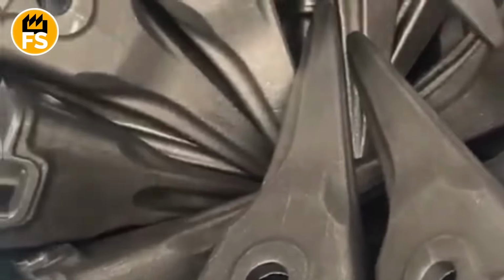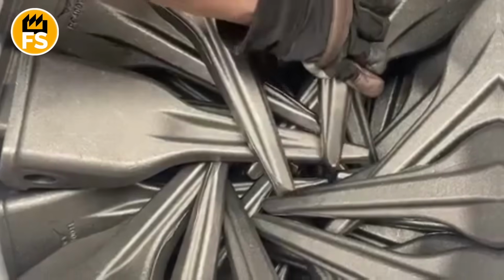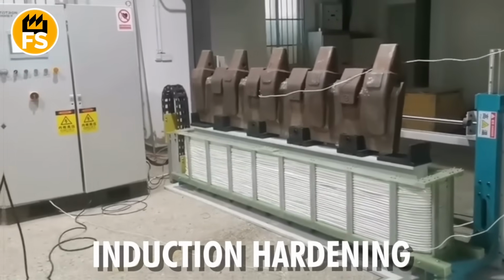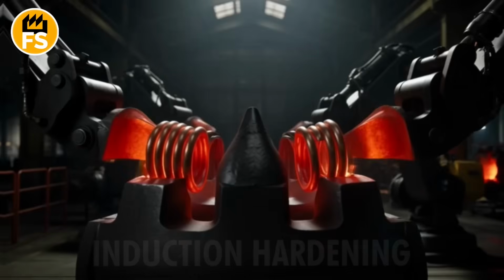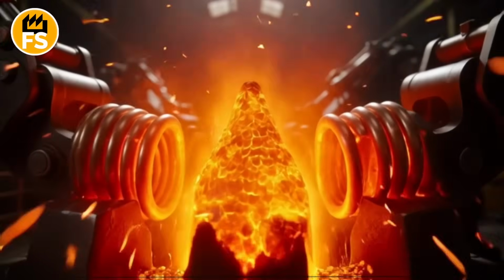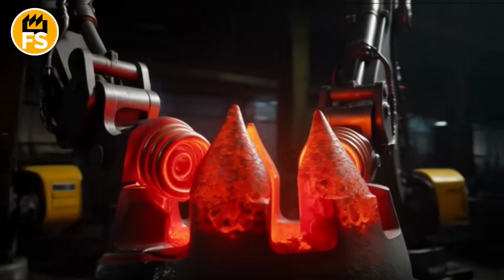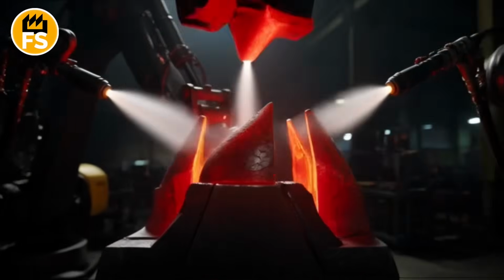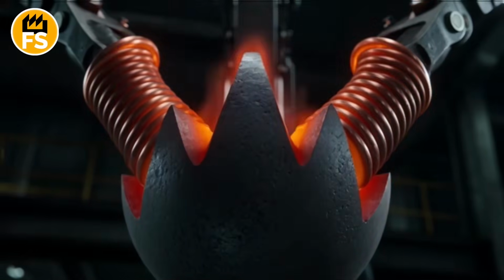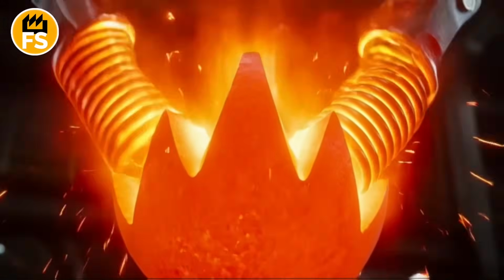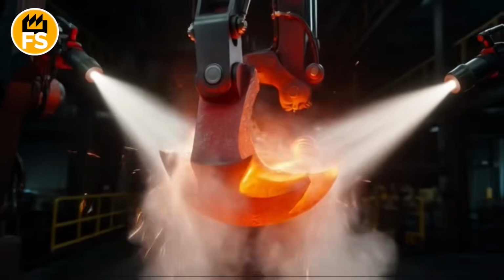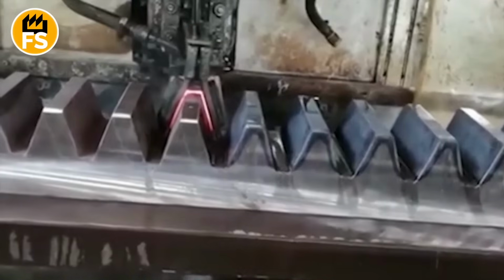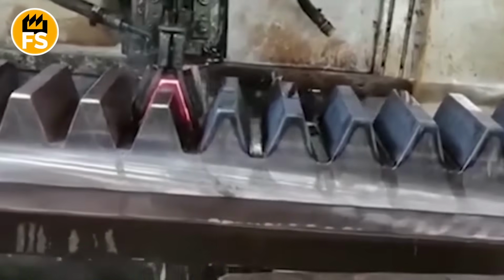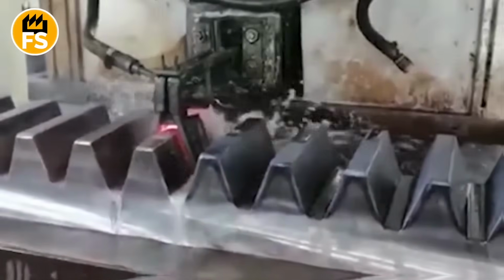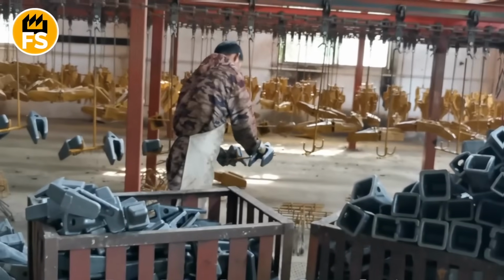But that's not all. Some manufacturers go with induction hardening, a process where the tooth surface gets heated by electromagnetic induction to temperatures between 2700 and 3000 degrees Fahrenheit in just seconds, then instantly quenched with water. This creates an ultra-hard surface layer about 0.04 to 0.08 inches deep, while the core stays soft and shock resistant. After heat treatment, every tooth goes through quality control.